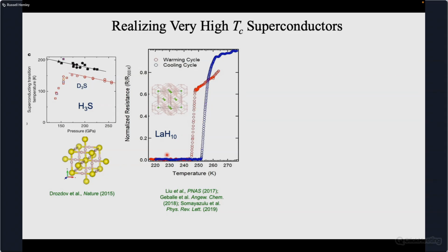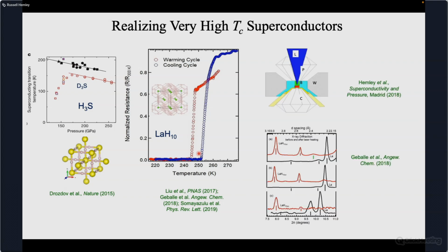All of these have atomic hydrogen in the structure, and this is the first measurement of the TC of this material, which is near room temperature, with the highest TC of around 260 Kelvin. This was actually quite a challenging experiment, much more challenging than the work on H3S, because one had to synthesize the sample inside the diamond cell, measure X-ray diffraction, and at the same time, on the sample without recovering it, measure some transport properties, for example, electrical conductivity or resistivity shown here.